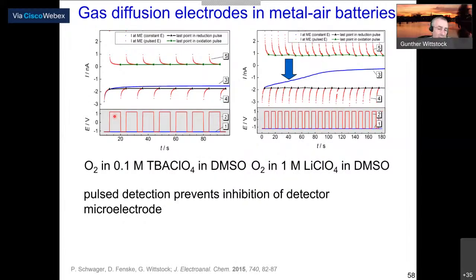Now we should detect the permeation of oxygen through that membrane, and we did that. Initially we started with tetrabutylammonium perchlorate in DMSO, and everything worked nicely. We get a nice current for the oxygen reduction at the microelectrode, depending on the permeation rate of oxygen. The same experiment made in lithium perchlorate, we couldn't get a stable current. The current always decayed and was going like this.